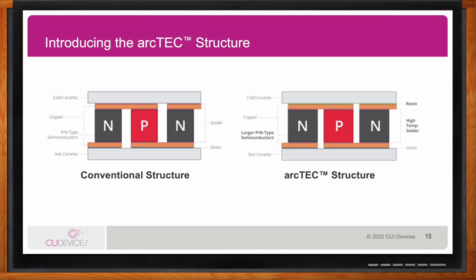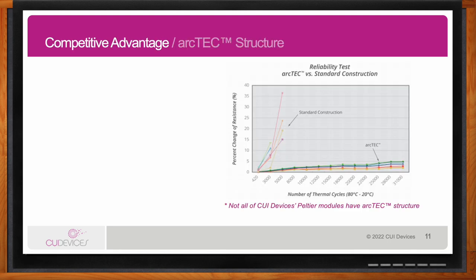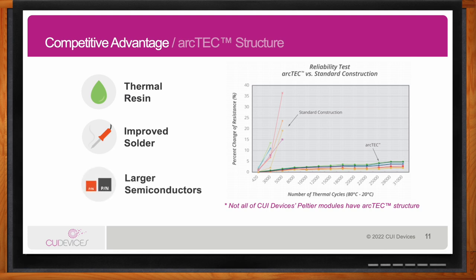So Rex, what does this arcTEC structure bring to the table in terms of benefits? Yeah, so it brings a lot of benefits. You know, I kind of mentioned the thermal resin layer. In addition to this thermal resin layer, we also use a high temperature solder rated up to 235 degrees Celsius. And we also use particularly large semiconductor pellets inside of our Peltiers to assist in uniform temperature across the surface of the Peltier ceramic. And I'll touch on that a bit more in the next slide.